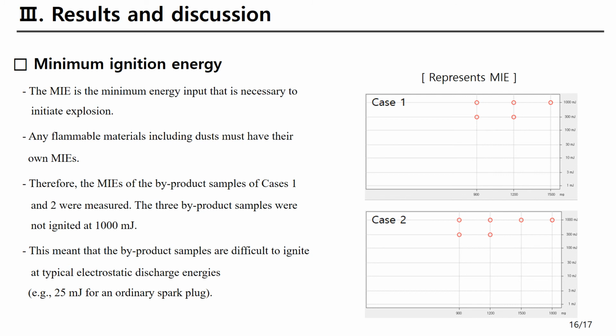The minimum ignition energy is the minimum energy input that is necessary to initiate explosion. Any flammable materials, including dust, must have their own MIE. Therefore, the MIE of the byproduct samples was measured. The 3 byproduct samples were not ignited at 1000 millijoules. This means that the byproduct samples are difficult to ignite at typical electrostatic discharge energy.